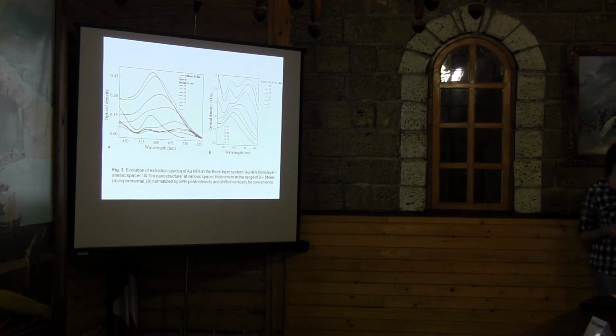I have also one question. Why do you believe that the second resonance is a quadrupole? The second peak. Yeah. We tried to calculate the same spectra with Mie theory, and there we have two peaks. But two peaks you will have for any nanoparticle deposited on a surface, because you always have in the layer of nanoparticles two different interactions, along the surface and across. It gives you a splitting of the degenerate resonance on any metal surface. Maybe here is one spectrum without the aluminum film, and there is one peak.